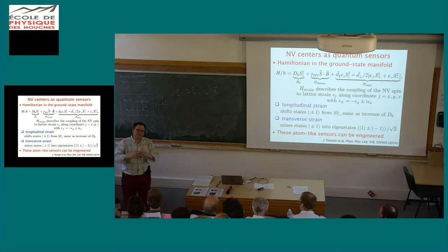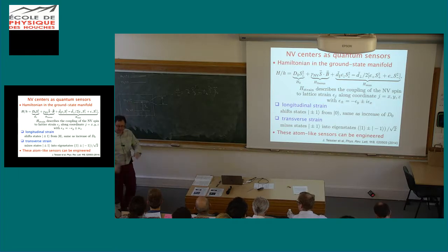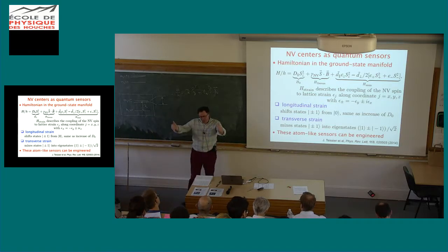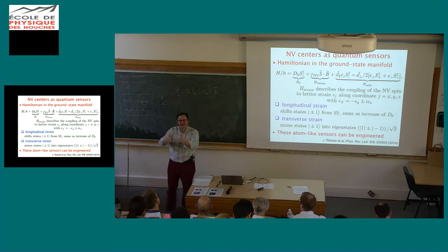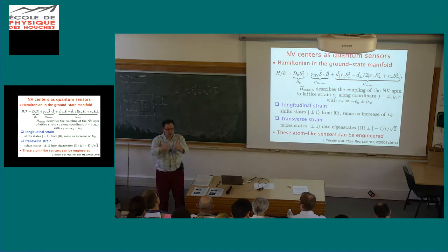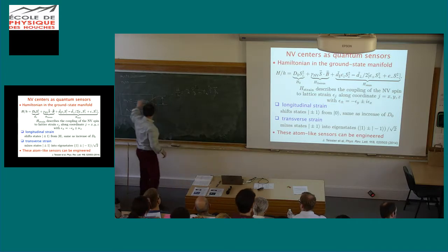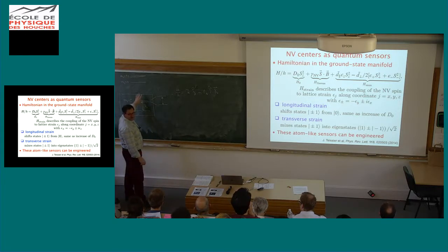Suppose, for instance, I have a hydrostatic compression. I will then keep the full symmetry of the defect. This means the level structure will remain identical. This will simply put the two electrons in the negatively charged center closer, so their magnetic interaction will be increased, and the separation of these two levels will increase.